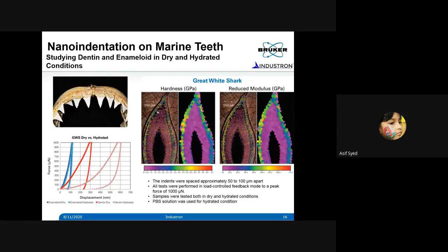So I think this was done at Washington State University, one of our collaborators, where they find this great white shark's tooth, do a cross section, polish it, and do hundreds of indents. You can see that in this image. All the dots you see are an array of indents, and the color of those dots gives you the hardness values at that location. Because it's all automated, you don't have to do anything.